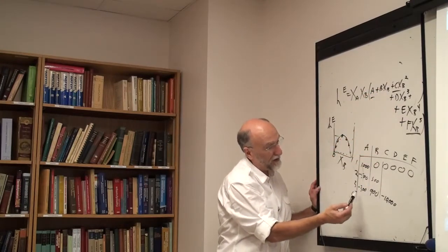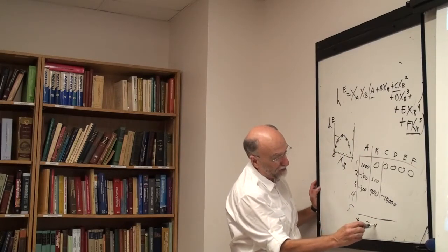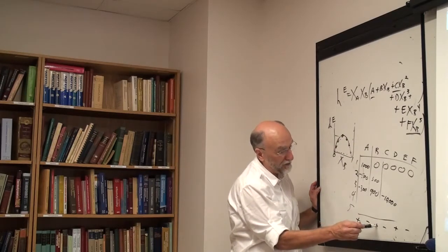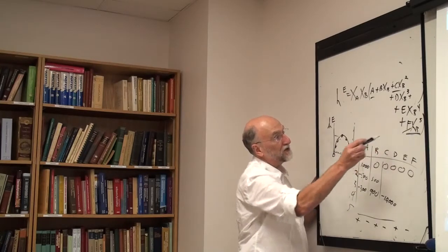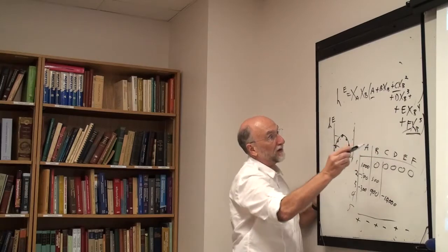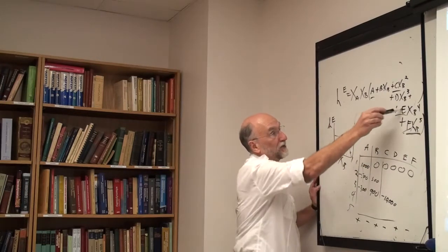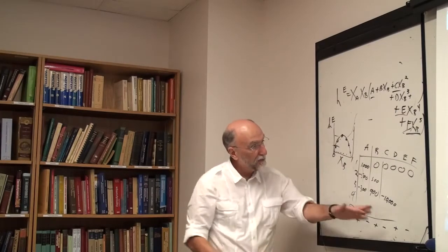And what you also find is, as you get to 4 and 5 terms, you generally find the signs going plus, minus, plus, minus, plus, minus. Your first term is positive, the second one's negative, the third one's positive, the fourth one's negative, and the reason is you've got to counteract it. If you want this F term to have any effect over here, where x is small, this term has to be very large, so it's way too big on this side, so the only way to get around that is to have this term negative to counteract it on that side. So you find your terms getting bigger and bigger.